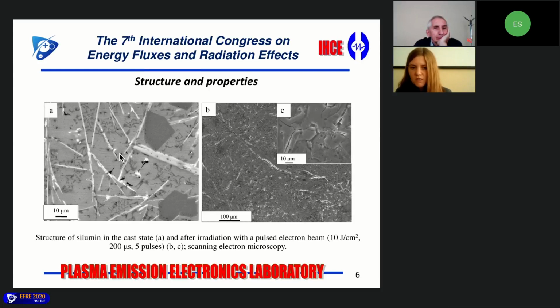The irradiation of silumin by a pulsed electron beam with an energy density of 10 joule per square centimeter leads to a slight melting of the surface, as a result of which no dissolution of silumin crystallites and intermetallic compounds is observed, and a large number of micropores and microcracks are still recorded.